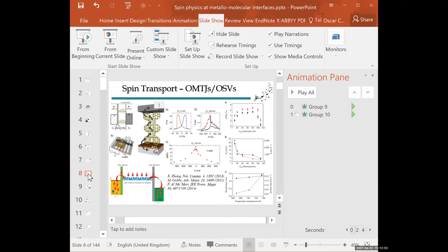Okay. As you will have noticed, we don't work on this, so I'm a bit unsure in this field. The first thing is that this never works unless you put an insulator layer in between one of the electrodes and the molecule. If the molecules are in direct contact with both electrodes, forget it, you are not going to see magnetoresistance. Well, you may see some, but it's going to be much smaller.